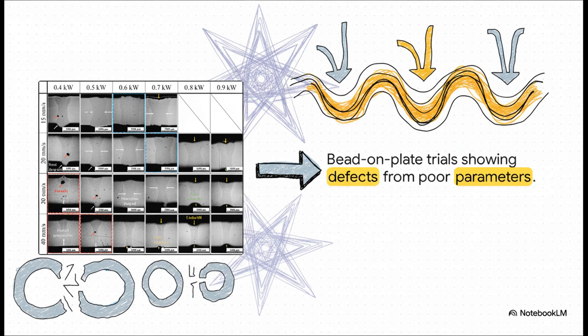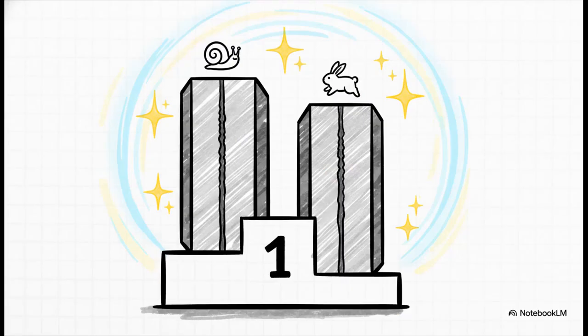When the energy density was too low, the metal didn't even melt all the way through, and that left these huge gaping pores and root dropouts. Just a mess. But out of that massive grid of failures, two absolutely perfect, defect-free conditions emerged. These were our finalists. The first one was welding speed of 15 millimeters per second paired with a laser power of 0.6 kilowatts. The second was slightly faster, at 20 millimeters per second with a slightly higher power of 0.7 kilowatts. Both of these produced gorgeous, full penetration welds with zero macroscopic defects when looked at under an optical microscope.